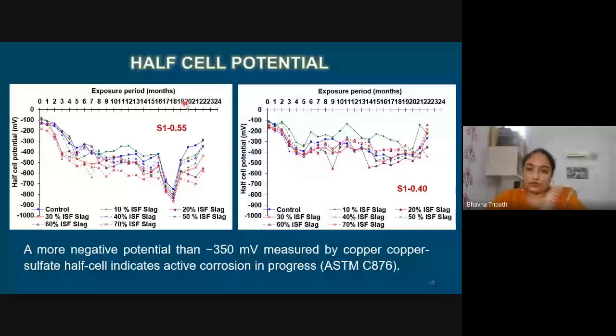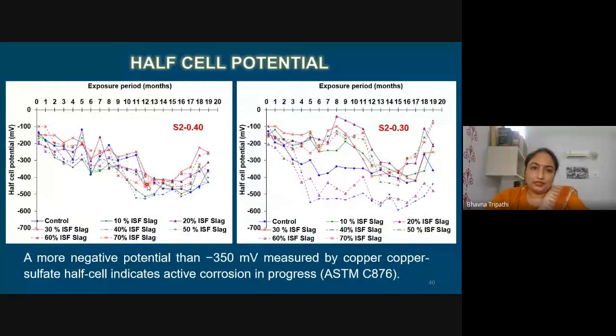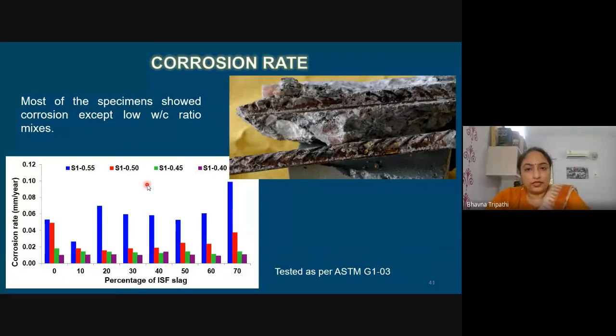The corrosion test was conducted for 2 years, by subjecting samples to alternate wetting and drying cycles of 2 weeks each. In between, the potential was also higher than minus 350. We can clearly see that after the 4th month, there are specimens showing more than minus 350 millivolts. These are other mixes. Finally, the corrosion rate was computed.